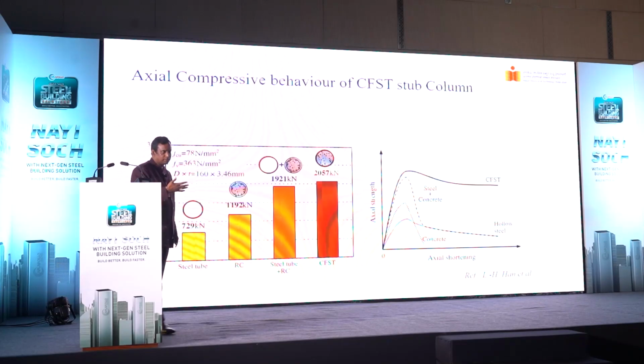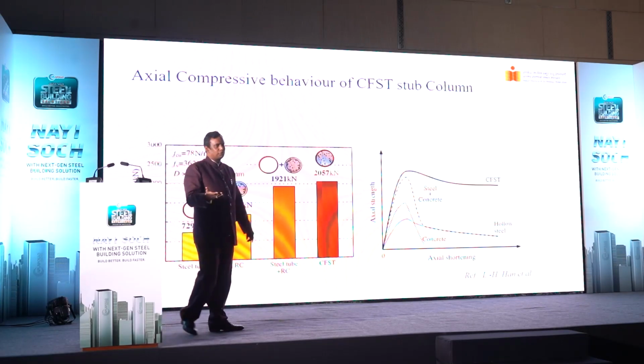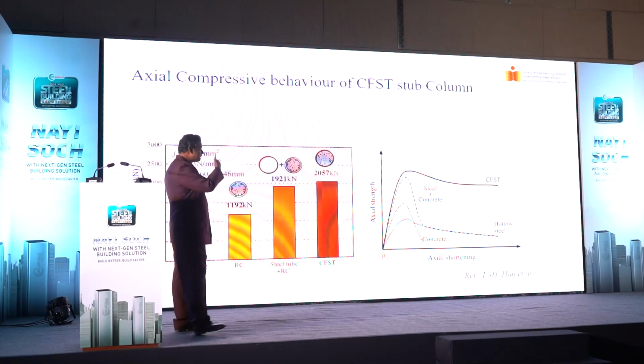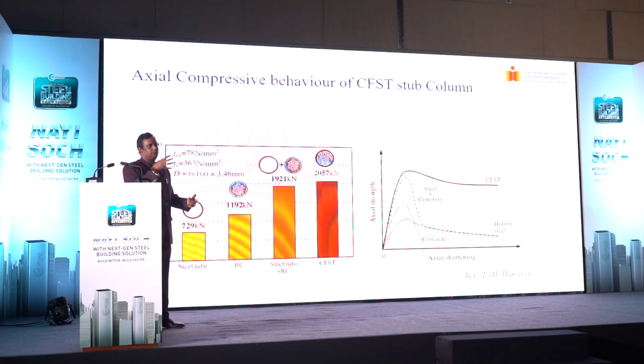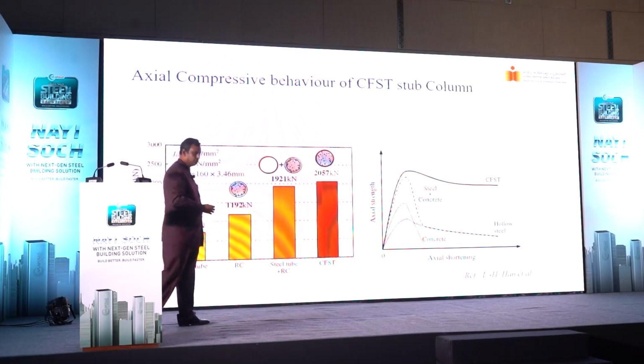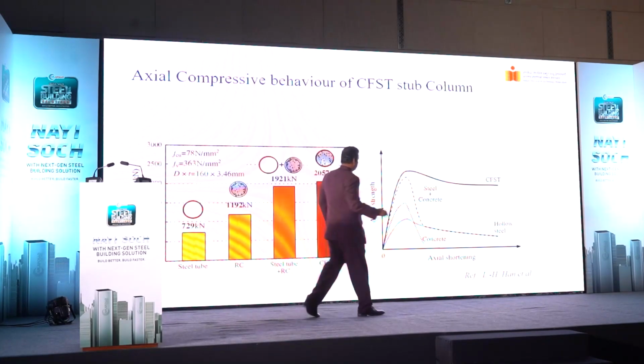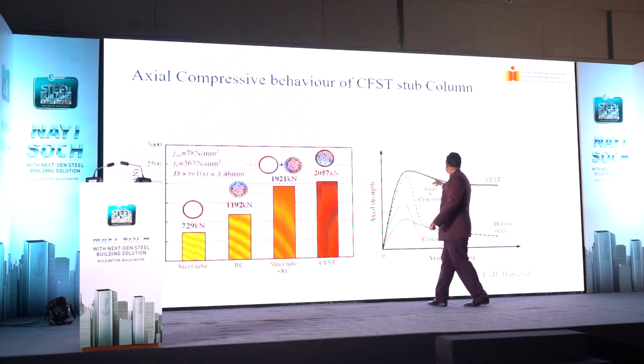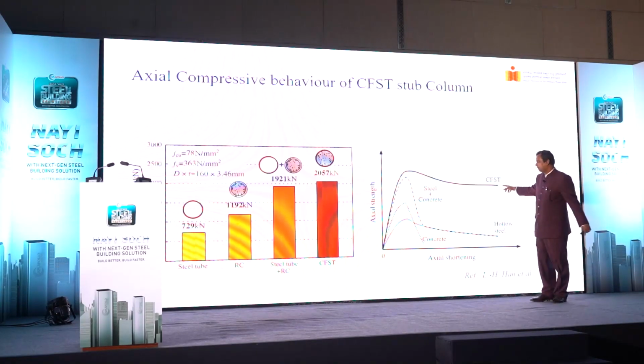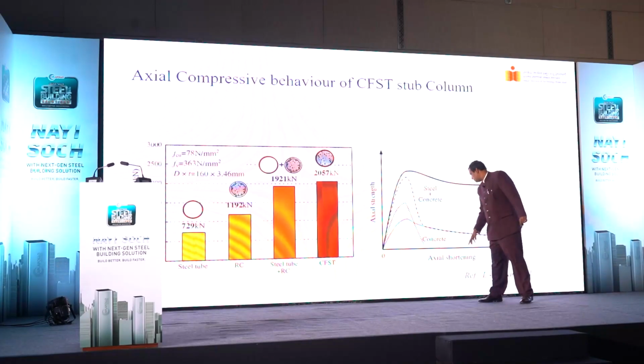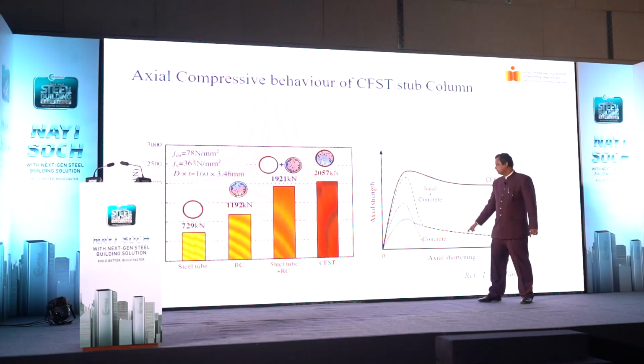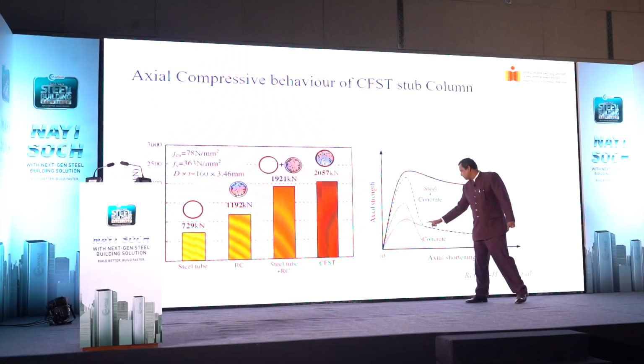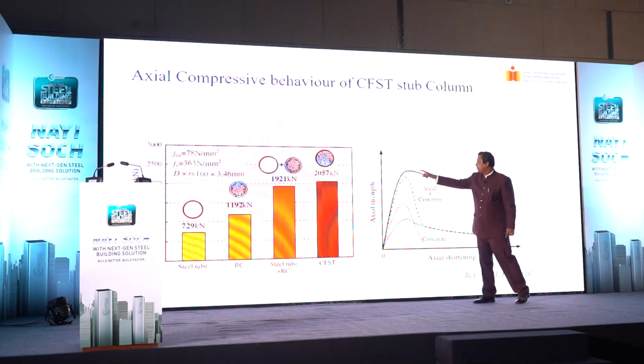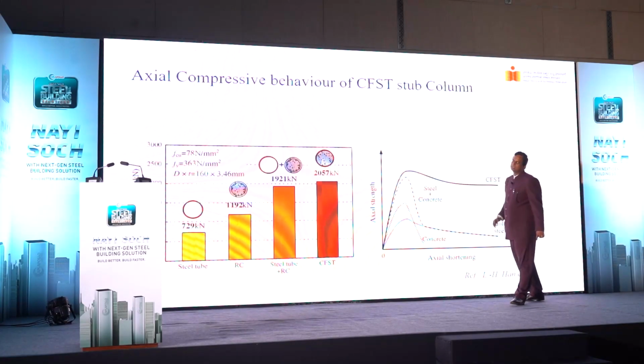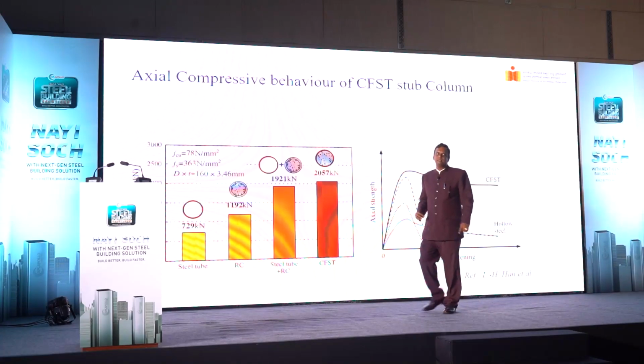So the load capacity increases. But that's not the moral of the story. The moral of the story is that when you put a steel tube filled with concrete, your ductility is very, very, very high. You can see that the ductility is very high. If you have concrete, it behaves like this. If you have steel, it behaves like this. You just add the two graphs together, and something comes like this. But when you infill, you can see a tremendous increase in ductility.